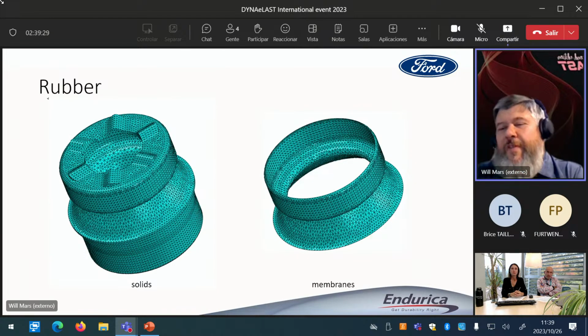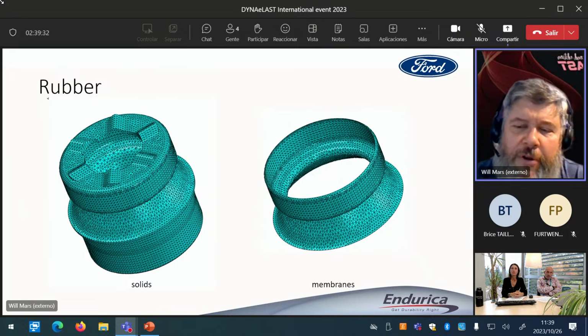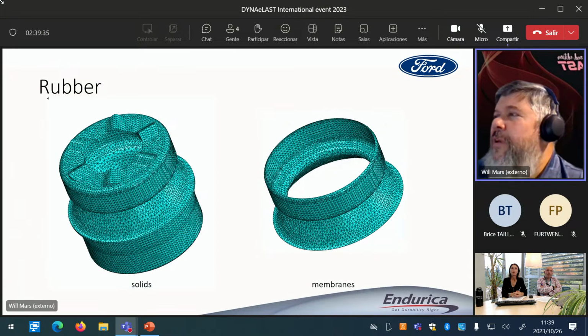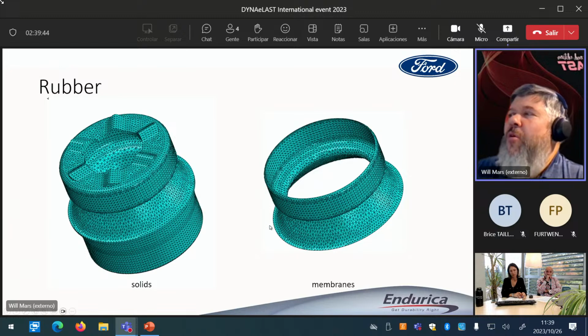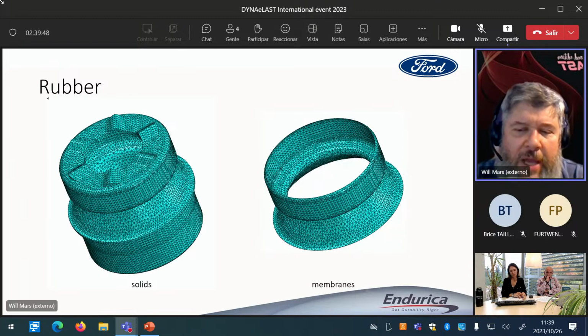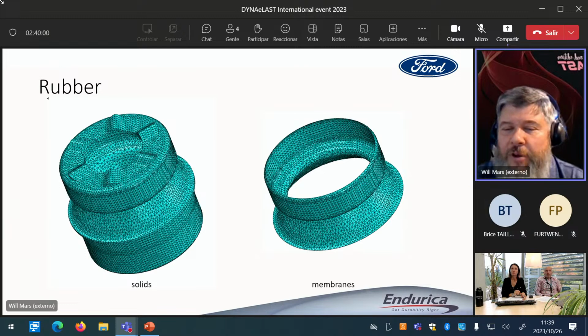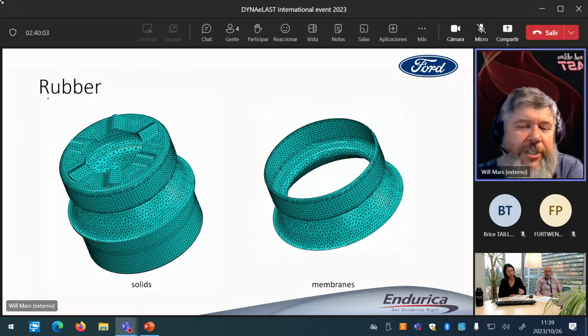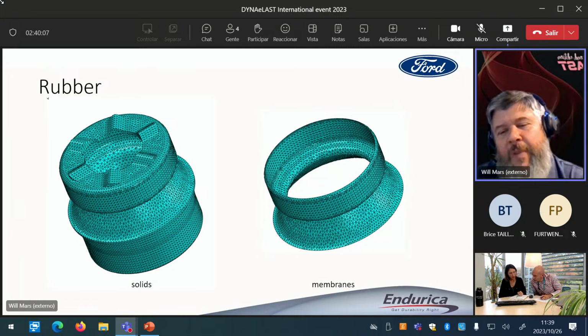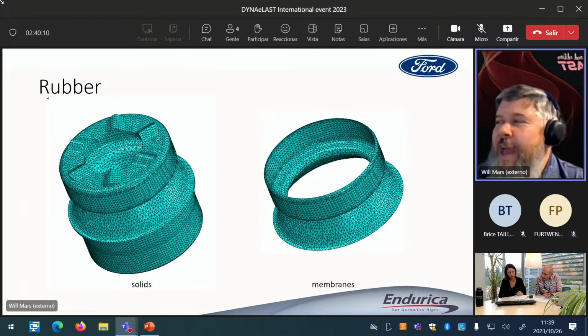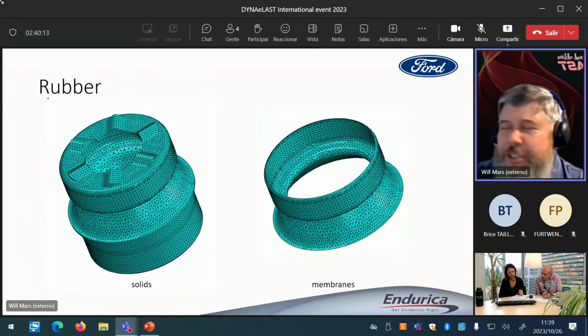And here's another view with the external can or cylinder removed. There's two meshes. We've analyzed both the solids and the membranes. We paved the surface of the solid model with membrane elements because that helps us to derive more accurate stress strain states on the free surface of the mount. And because we expect cracks to initiate on the free surface, we want to get accurate stresses and strains on that free surface as much as possible.